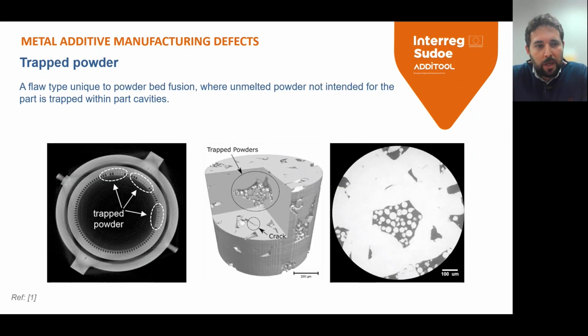Trapped powder is a defect produced when unmelted powder is trapped in inner cavities of the part. As you can see here, this is also a CT cross-section, high resolution CT, where you can see the shape of the powder within the melted part. This is another cross-section of the computer tomography where you can see some cavities without trapped powder, more darker, and with trapped powder.